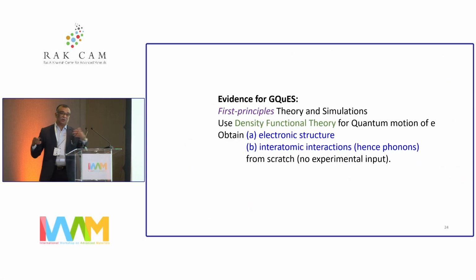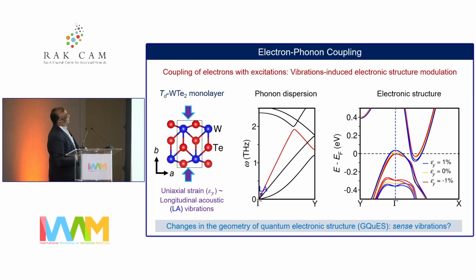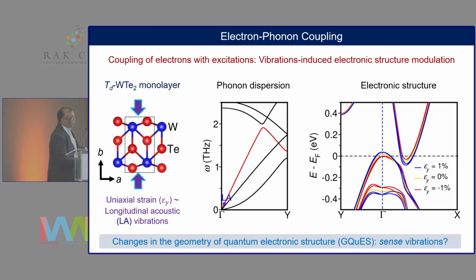So until now, it was all a sort of analysis. Now we use first principles calculation to demonstrate that indeed in some real systems, this will be an observable feature. So we start with the material which was studied by Pablo Herrera's group, namely non-centrosymmetric tungsten telluride. And if you oscillate this using this strain mode, as I have shown, that mode, vibrational mode, actually corresponds to longitudinal acoustic phonon, the vibrational frequency. And it's a fairly low frequency mode.